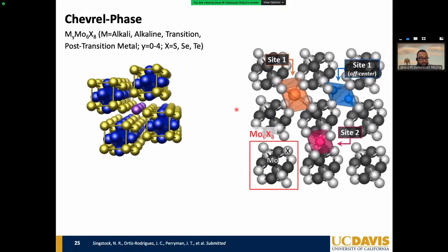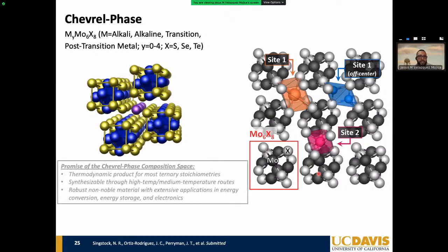And in recent work that we published in JACS, actually I have to update that reference, thanks to our collaboration with the Musgrave group, we have been able to elucidate that there are even more areas in which you could intercalate within this framework. Actually, the site shown here in magenta, utilizing some of the guidance from theory, we've been able to synthesize using some solid state chemistry. So the reason why we're excited about it, well, one of the many reasons, is because what you're seeing here is the thermodynamically stable configuration. So what that means is that if we are going to screen different types of electrocatalytic reactions, we could just change the intercalant at will, and we won't have much issues with stability.